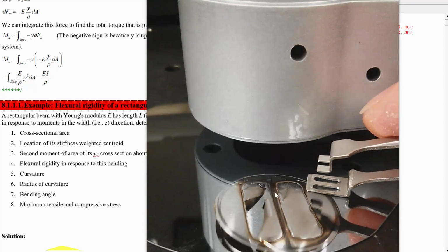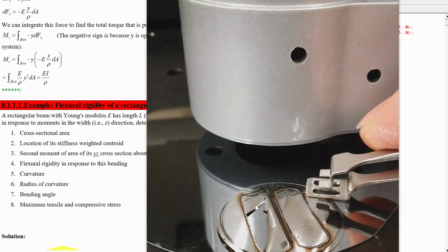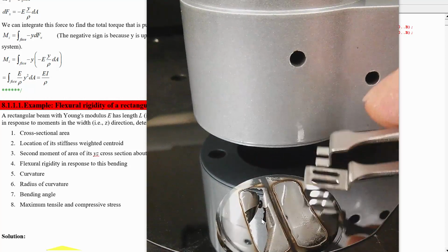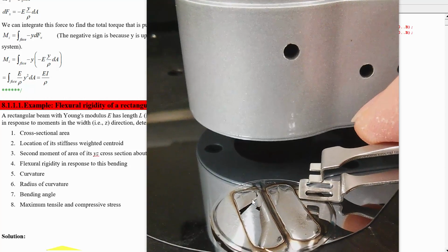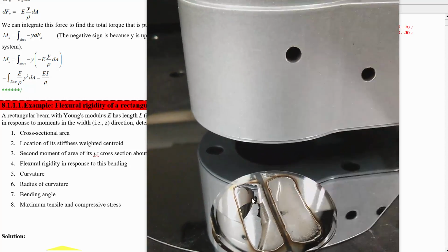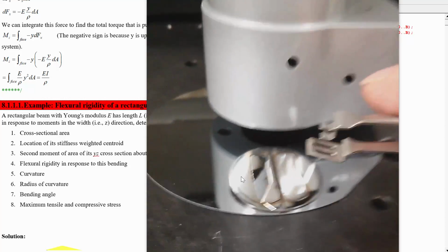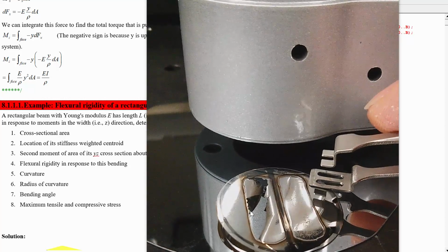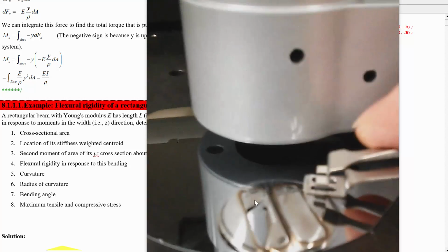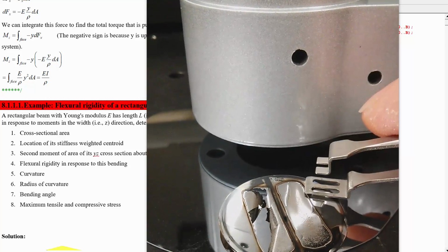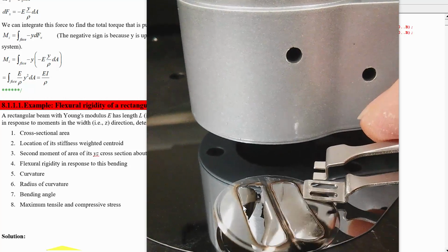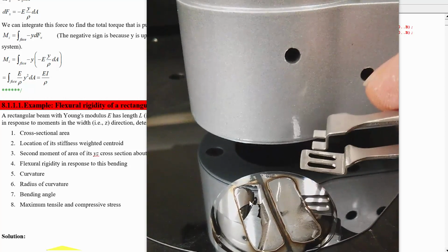Here's an example of me doing this with a piece of single crystal quartz that's been coated with some molybdenum here during the PhD work that I did at McMaster. And you've got this little membrane of quartz, which is about 7 microns thick. And because it's that thin, even though it's single crystal quartz, which is a very brittle substance, it is able to curl and uncurl no problem. So it curls up from the difference in strain that's been put on each side of it and is able to flatten out and go back, no issue.